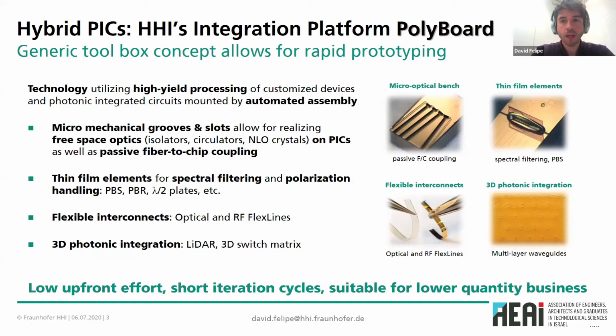Another very interesting feature is what we call flexible interconnect. The components that you see here on the top side, the U grooves that I showed and these thin film elements, are fabricated on top of a silicon substrate. And what we can do is peel off the polymer to fabricate these flexible interconnection methods. They can be either optical or also high frequency, since polymer materials show a low dielectric constant, which is good for the high frequency capabilities of, for example, coplanar waveguides.